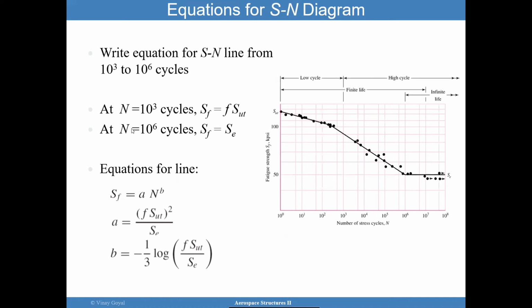So you can do these calculations graphically, is one approach. You can write the equation for the SN line that goes from 10 to the 3 to 10 to the 6th, and then from here it is constant after 10 to the 6th. That's one approach. The equation of this line is basically fatigue strength equals A times number of cycles to the exponent B. And A can be approximated as (f·SUT) squared divided by SE. And then this same ratio without the square goes in this B here. So with very limited information, you can actually construct the SN diagram for a particular material.